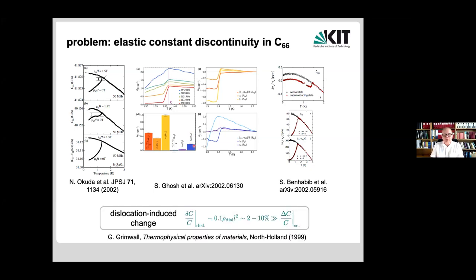The only explanation, if you wanted to rescue the story I've just told you, is that it's actually known that the dislocations change the elastic constant quite significantly. You need to know their density and size, but typically even for good materials, you find that there's a 2% up to 10% change in the elastic constants.